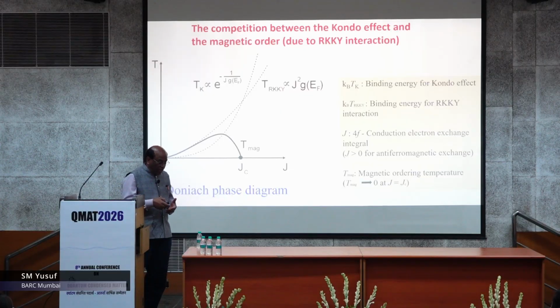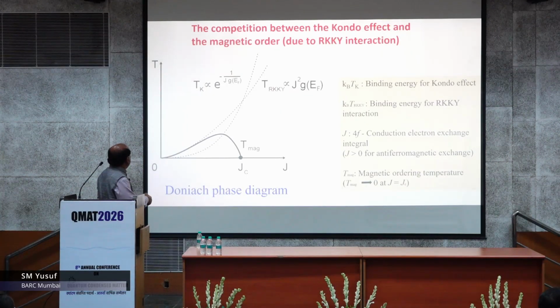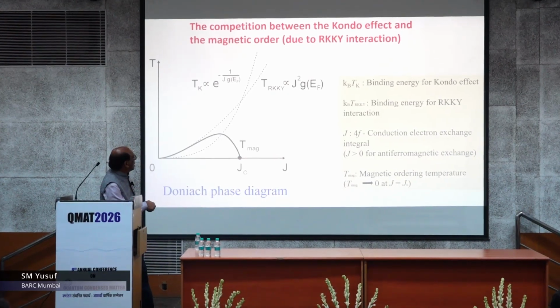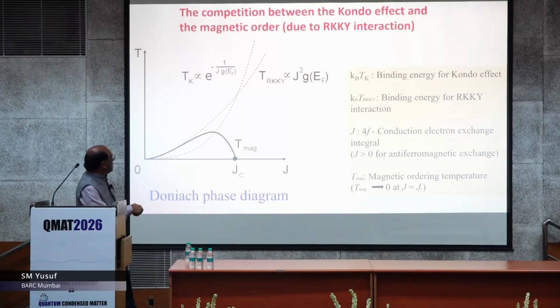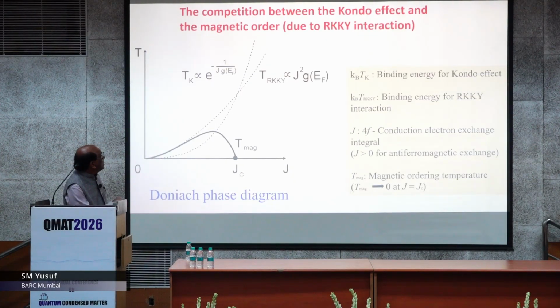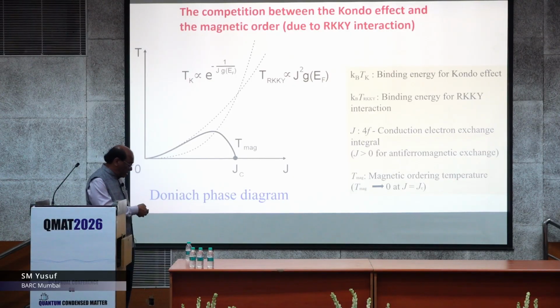Yet another way the competition between moments can take place. Suppose you have a system where there is a magnetic order due to RKKY interaction, and the strength of the interaction between this 4f and conduction electron is measured by J. That is what J is plotted on the x-axis, and this is the thermal energy k_B T. You see there are two terms. One is the magnetic order, that is the RKKY interaction strength, defined by this line, and this is the Kondo effect strength. In both places you have J. So beyond a certain J value, that is at J equal to J_C, you do not see any magnetic ordering. It gets destroyed. So this is yet another case, the famous phase diagram, that tells that due to the competition, the frustration between these two competing terms, the magnetic ordering is destroyed in a system.